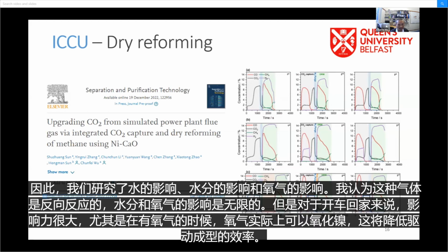So we investigated the influence of water, basically the influence of moisture and the influence of oxygen in the flue gas. I think for the reverse capture reaction, the influence of moisture and oxygen is quite limited, but for dry reforming, the influence is significant, especially when there's oxygen. The oxygen could actually oxidize the nickel, and that will reduce the efficiency of dry reforming.